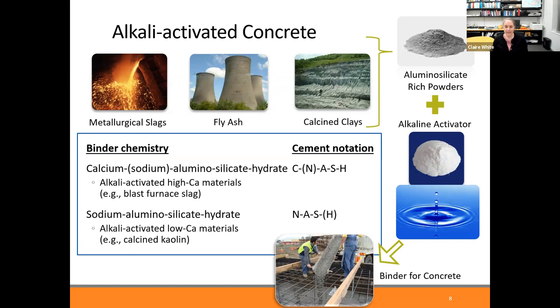And this is alkali activated concrete down here that's actually been made with a combination of blast furnace slag and also fly ash. It behaves at the macroscopic level in a very similar fashion to Portland cement concrete, but the fundamental phases within this material are different. And so we want to understand how those phases impact long-term performance of this material.